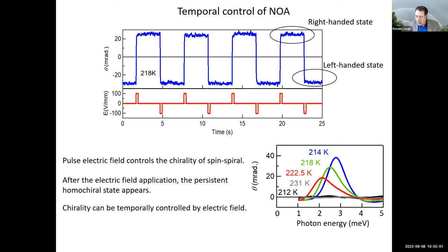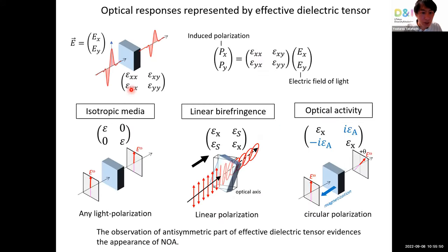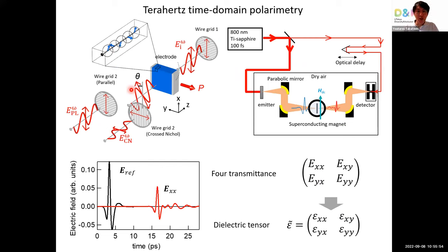Okay, yeah. And we have a couple of questions from Gyujian Wang. He asked if you're using single crystals in the experiments. He has several questions, I'll ask them one by one. We use a single crystal for both experiments. In the case of the cupric oxide, for the terahertz measurement, we need a larger single crystal. Typically, we use 2 or 3 millimeter samples to get the optical constant of the materials. We cut the crystal, and I don't have a picture, but typically a rectangular shaped crystal is used, maybe using the 110 plane of this crystal.